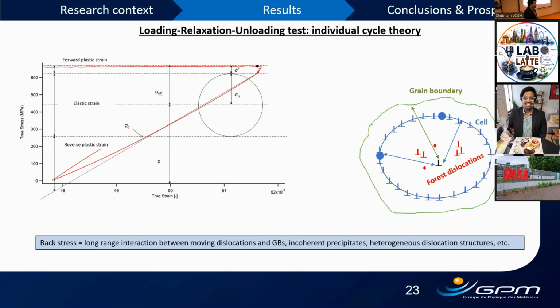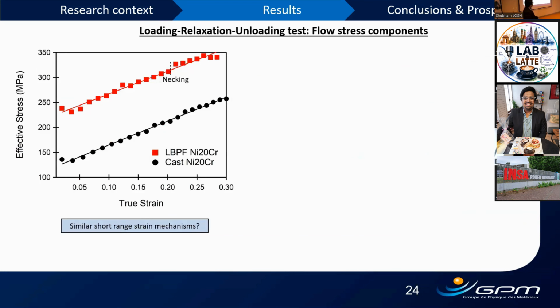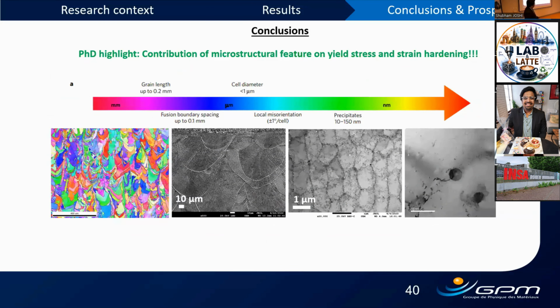Because sometimes you have 8 orders of magnitude between the minimum and the maximum value, which is quite huge. So, yes, when it's 10 to the 5, you consider that it's already infinity. Exactly. So that means that if you want to get even more simplified modeling, you can squeeze this term from the model for the LPBF material. Yes, that's your conclusion. You can even have a more simplified law.